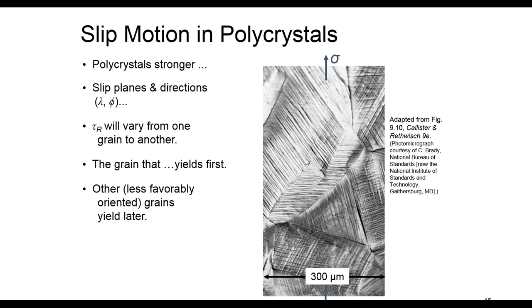So if we have a group of dislocations which is under stress, they go, say, for example, to the right side of this grain. When they bump to the grain border, the grain border acts as a barrier, so it will stop it to some extent. That's why we expect polycrystals to be stronger than single crystals.